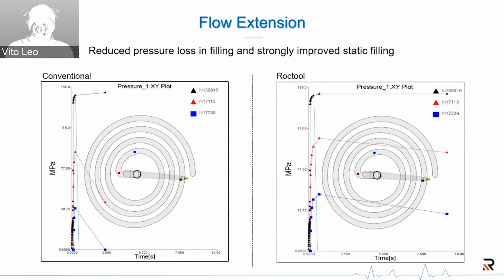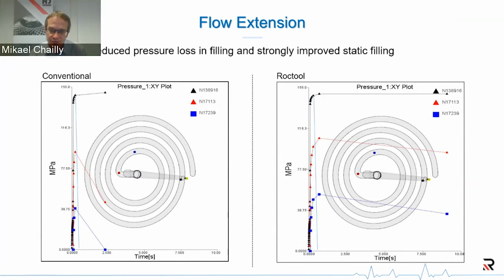Sure. So for the flow extension, we can see that we have a reduced pressure loss during the feeding. Basically, having the same pressure at injection locations, we gain about 15% on the first pressure sensor and about the same value on the second one. So we have a better pressure transmission during the filling within the cavity.